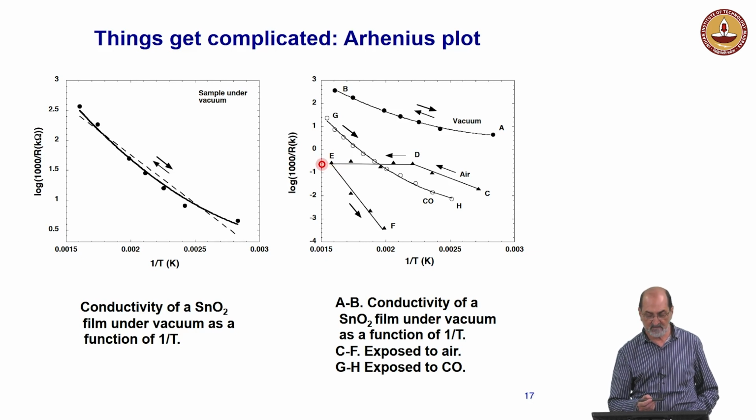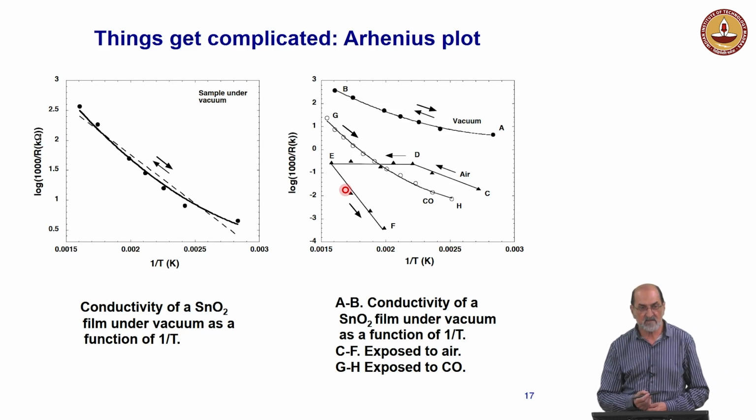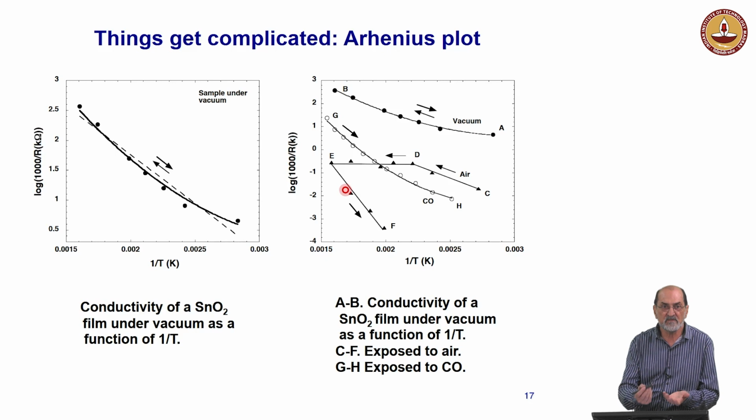Something new is happening. Maybe the oxygen starts getting into the grains and the conductivity does not increase as it should. There is a competition here. In principle, since things are activated, the resistance is going to decrease, so the conductivity is going to increase, but at the same time oxygen is pushing in the other direction, and the competition between those is quite close, so the resistance almost does not change.